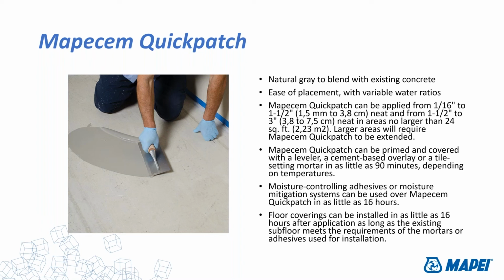Mapecem Quickpatch is a sanded product, which makes it a little more difficult to get to that thin layer. And it's sometimes not your last step. Because it is sanded, it does create a little bit of a rough surface. If you're installing something like a 2 millimeter rubber or sheet vinyl or resilient flooring on top of Quick Patch, you might see the texture of that through the surface. So you might want to skim it with another high moisture product after you install it.